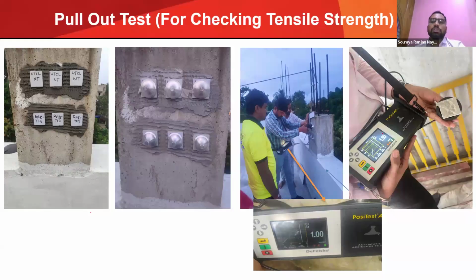This machine itself costs around 2 to 2.5 lakhs. And if you see, we apply the tile adhesive and 50 mm tiles with the tile adhesive. Then we let it set for 7 days or 28 days, and we can do it in 7 days also. And after that, we will fix these.